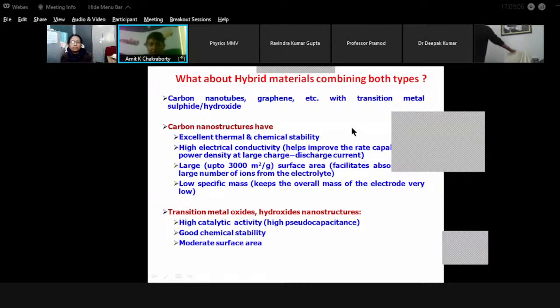They have high electrical conductivity and large surface area. Activated carbon especially has extremely large surface area. Carbon being a very light element, its density is very low, so specific mass is very low. Whereas transition metal oxides, sulfides, hydroxides, etc., are very good in terms of catalytic activity because they take part in the redox reactions. Most of them also have good chemical stability and moderate surface area if you make them into nanostructures, depending on the structure that you make.